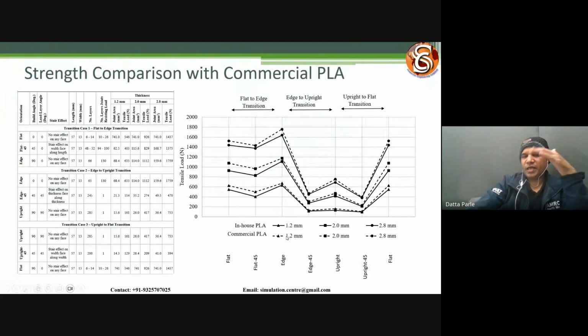Maybe commercial PLA, these dotted lines, showed some higher load capability than the in-house, maybe because ours was in segments, and we are not sure what PLA granules or raw material they use. We tried matching that property with the granules, but maybe that is one of the reasons for the variation. It also showed similar trends, all strong and weak groups. Additionally, we did some more analysis on why they are not matching, and this probably could have been done for the earlier part also.